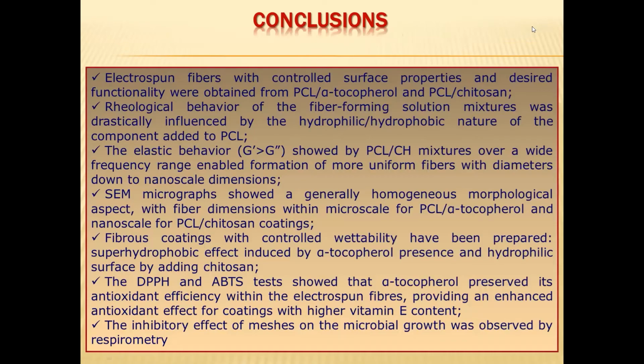In conclusion, electrospun fibers with controlled surface properties and desired functionality were obtained from PCL tocopherol and PCL chitosan. The rheological behavior of the fiber-forming solution mixtures was influenced by the hydrophilic or hydrophobic nature of the component added to PCL. The mixtures of PCL with chitosan showing predominantly elastic behavior enable the formation of more uniform fibers with diameters down to nanoscale dimensions, while the PCL alpha-tocopherol system had microscale dimensions in the diameter of the fibers.